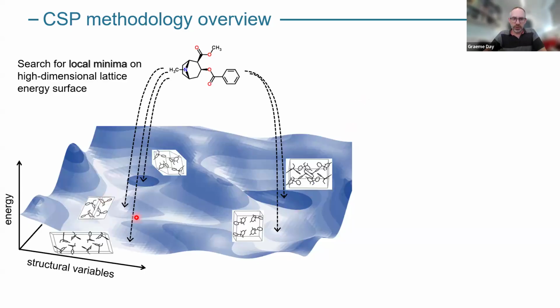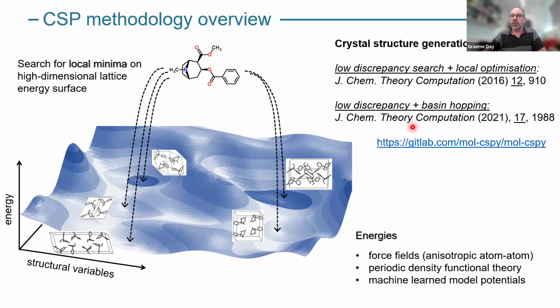So each of those minima, again, corresponds to a distinct crystal packing. We want to enumerate all those packings, which in itself is a difficult problem. And then we want to rank them, which is also a difficult problem. The way we go about searching the energy landscape, we take the approach of doing this as broadly as possible. So we use a low discrepancy search, so all of our initial structures are as separated as possible in the initial degrees of freedom.